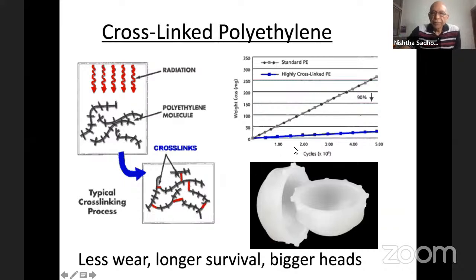What that does is, in effect, it takes the wear to a really low value. So this is the graph plotted for the standard polyethylene. As time progresses, it's a linear progression upwards. Whereas with the passage of time, the wear of a highly cross-linked poly is, compared to this, extremely low. Thereby, much longer survival, and very important from a practical point of view, the polyethylene thickness does not have to be enormous to last a patient a couple of decades. Because of the cross-linking wear characteristics,